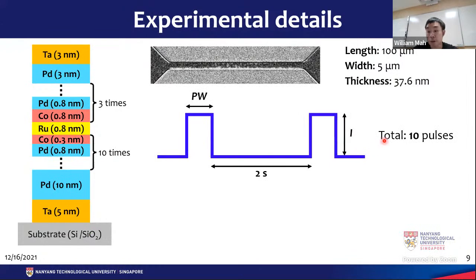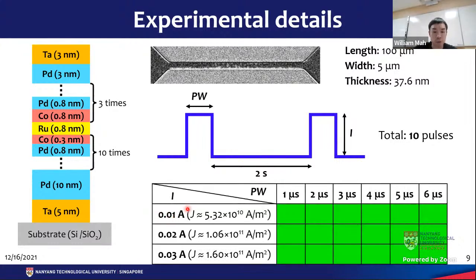I apply a total of 10 pulses. Each pulse is 2 seconds away from each other. I represents the current strength. PW is the current pulse width, which is the duration of the current pulse. So the current strength is varied from 0.01 ampere all the way to 0.03. Pulse width is varied from 1 microsecond all the way to 6. I have tried every single combination, but in this talk, for the sake of time, I'm only going to talk about specific cases.